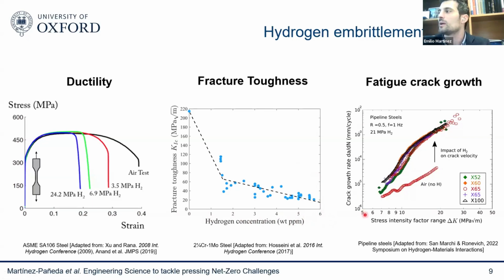And this is fatigue as well. You may remember fatigue from the second year course on statics and structures. This is the crack growth rate, so the crack speed. You can see here, this is the response in air. This is a log plot, by the way. So you can see that we increase the crack speed by more than an order of magnitude whenever we expose these pipeline steels to hydrogen gas or any hydrogen-containing environment. So that's a problem because, well, hydrogen is everywhere, first of all. But second of all, we want to store and transport hydrogen gas. This is a key element in the energy transition. But when we do so, our metals are going to become very brittle. And you can see here that the reduction is really dramatic. A very small amount of hydrogen makes orders of magnitude change in fracture and fatigue resistance.